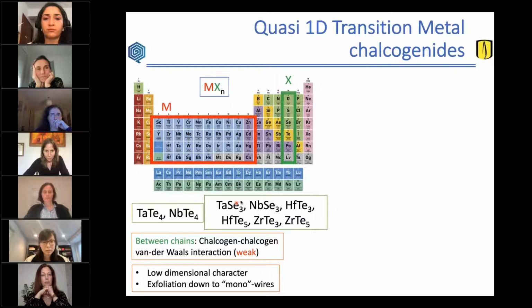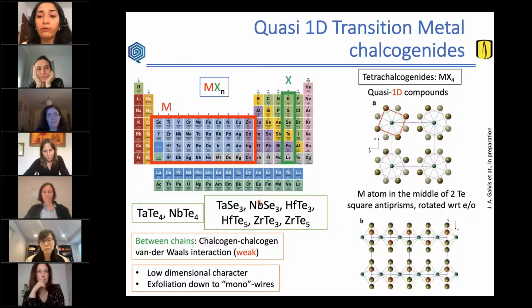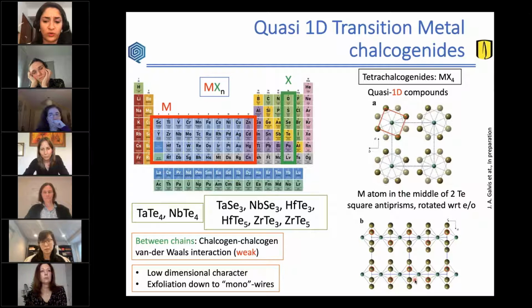But also we have some trichalcogenides, which have been studied in more detail in the past. So we will focus on the tetrachalcogenide compounds, which form these quasi-1D chains. As you can see here, for example, in NbTe4, we have chains of niobium atoms, which are these green ones, surrounded by squares of tellurium atoms, and these structures form chains which couple weakly by this van der Waals interaction with other chains, forming these quasi-1D structures for this compound.